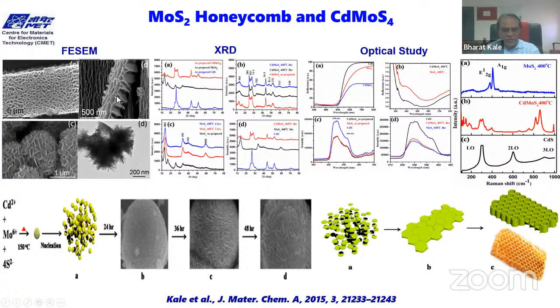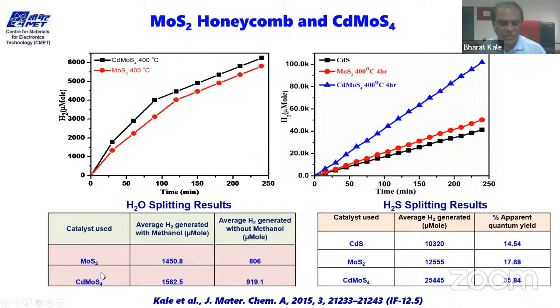Then we thought that MoS2 is a good product, like cadmium sulfide is a good photocatalyst. Whether we can have a single phase compound of cadmium molybdenum sulfide, and it helped a lot because we could tune the band gap into the visible region in an efficient way, and we found that we get good hydrogen evolution. For CdMoS4 it is 1562.5 micromole, and for H2S splitting it is much more, around 25,445 micromole. H2S splitting generally gives good photocatalytic activity in sulfide kind of semiconductors, which we observe.